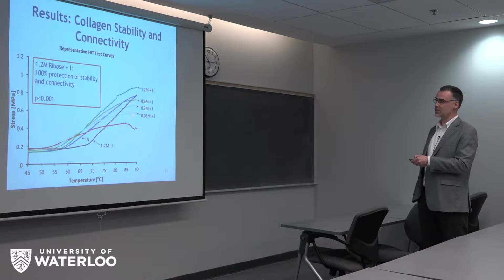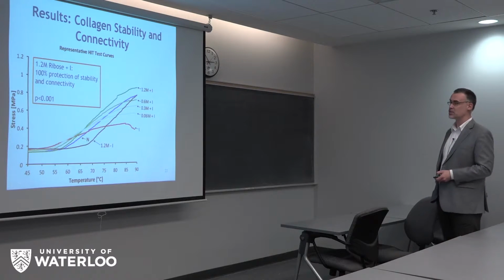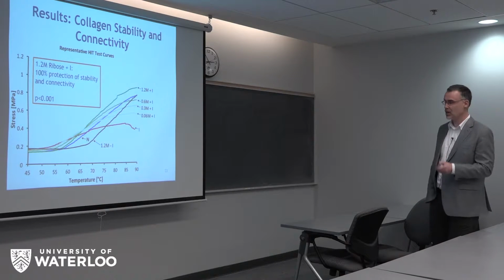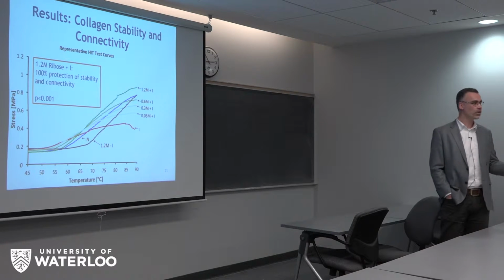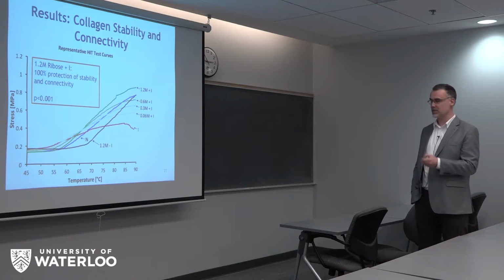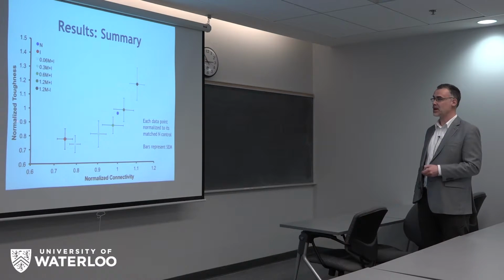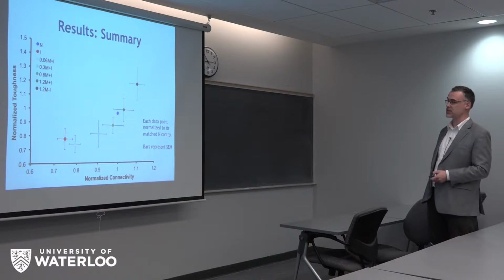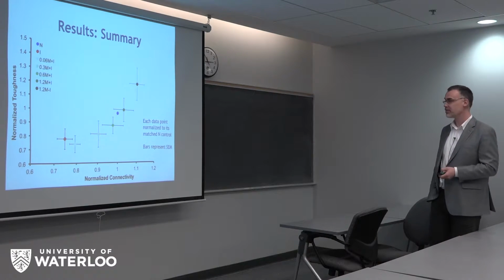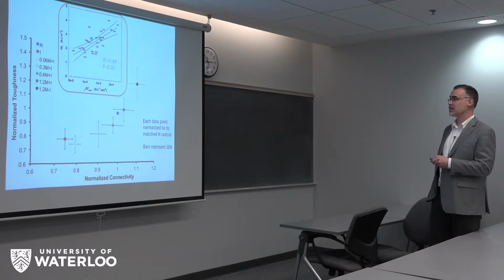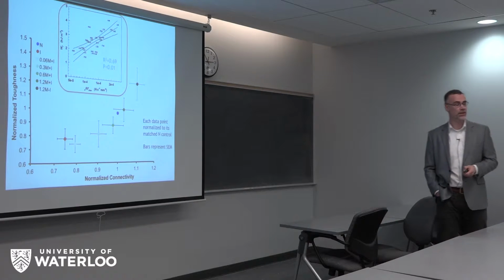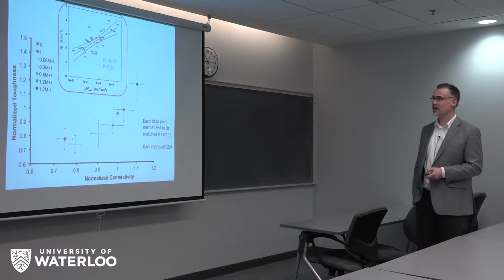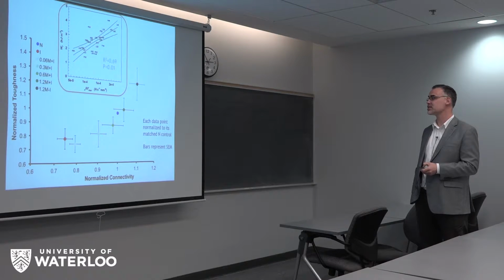Whereas when we apply the increasing concentrations of ribose, we're able to bring the slope back up. The thermal stability is pretty similar. And so we've effectively protected the collagen network. That's not to say that it is normal collagen at all, but the connectivity and the stability have been protected. And if we plot normalized toughness versus normalized collagen connectivity, we see this relationship, which is actually very reminiscent of that aging work that I told you about earlier. So we think we have a good idea about how this system works.